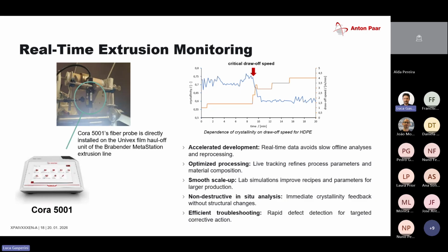Because what typically happens is if the draw-off speed is very slow, so if I extrude at a very slow speed, the polymer has a lot of time to cool down and to crystallize. So here you can see if the draw-off speed is very low, the crystallinity is high. If I extrude very fast, then the crystallinity is very low. But in here we have this critical draw-off speed. So even if I change a little bit on the extruder speed, the crystallinity changes quite a bit.